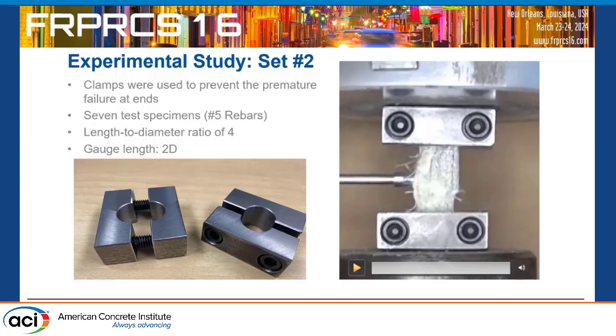And that's what's happening. And you saw a quick shift as well. First of all, we were able to avoid crushing at the ends successfully, but the shifting was not solved. And that's another problem. So we need to avoid that shift.